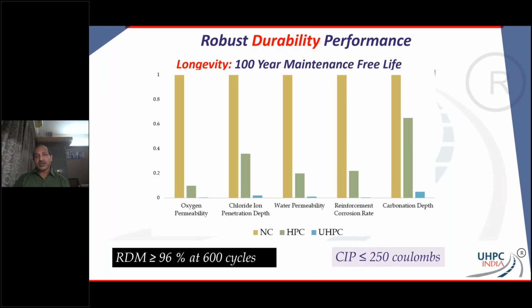Next, I'm going to show you this particular screen where the durability performance of UHPC is shown, and you will see that this is where the word performance comes from in UHPC. The durability characteristics are excellent. Here is a quick comparison of penetration, water permeability, corrosion rate, etc. In yellow is where normal concrete is, green where high performance concrete is, and see if you can find those little blues down below. That's where the UHPC is. So UHPC is extremely watertight.